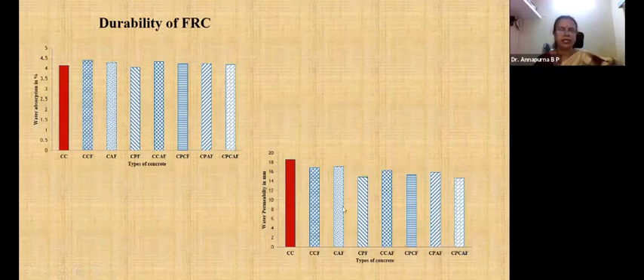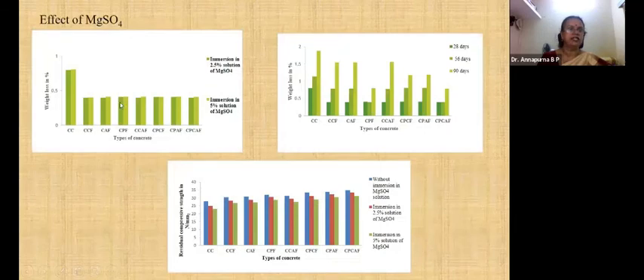So this is water permeability. Permeability in conventional concrete is more, but with the fibers the permeability is reducing, and in the presence of plastic fiber, it is reducing the maximum. Then magnesium sulfate. With immersion in magnesium sulfate, all these fibers show less percentage loss in weight compared to the conventional concrete, because they are not showing much reaction.